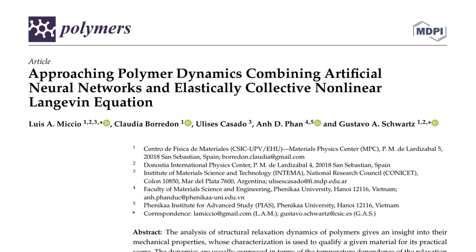The ECNLE model describes the dynamics of glass-forming liquids using a hard sphere fluid and quantifies the dynamic free energy. The model considers interactions with nearest neighbors and cooperative motions of particles beyond the first shell. The relaxation times are calculated using Kramers' theory. The ECNLE model assumes equal weighting of local and collective dynamics, but the authors acknowledge that adjusting the relative importance of collective elastic contribution could improve the accuracy of the model.